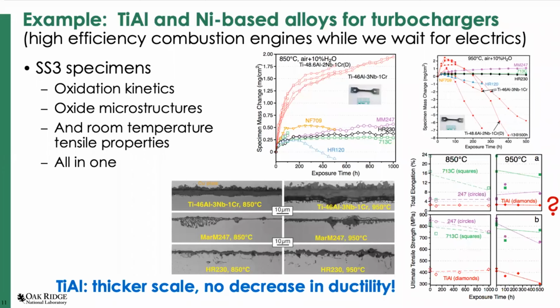And again, with these tensile specimens, we can measure mass change. We can report kinetics. We can section them, look at the reaction products. Again, these are all from SS3, sort of 25 millimeter long specimens, and then we can break them. And the interesting thing about this study was that we were expecting to see that the titanium aluminides were going to embrittle during these exposures at 850 and 950 degrees C, for 1,000 hours at 850, 500 hours at 950. And in fact, they didn't lose any ductility. So surprised, and apparently those materials have come a long way. Certainly, they had thicker reaction products, but we didn't see the embrittlement that others had reported.